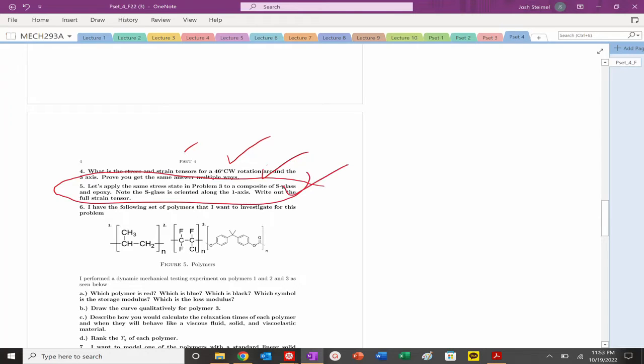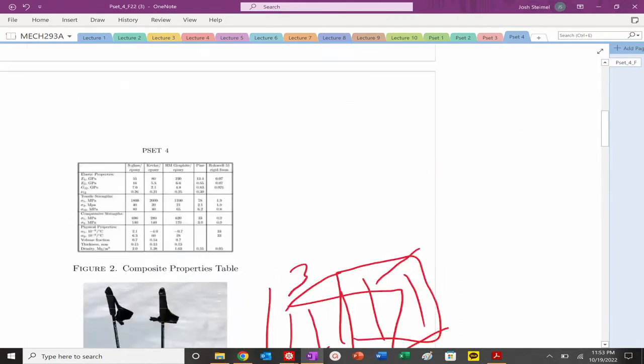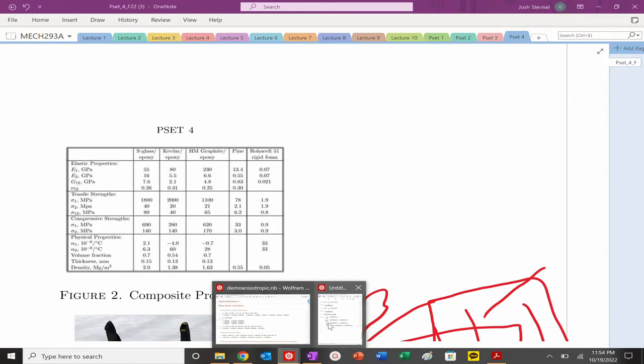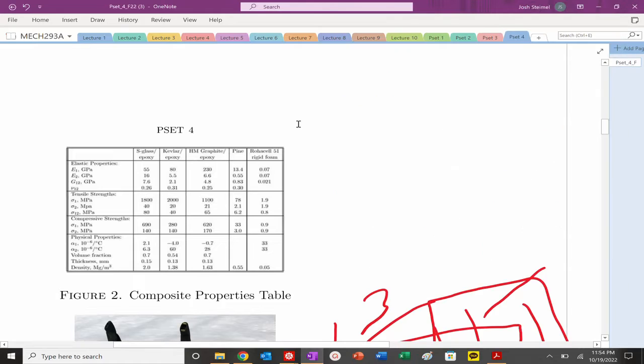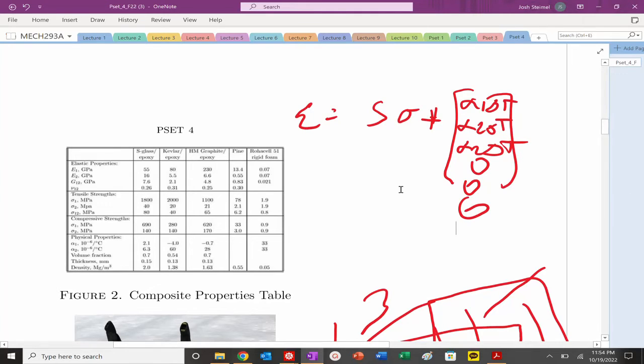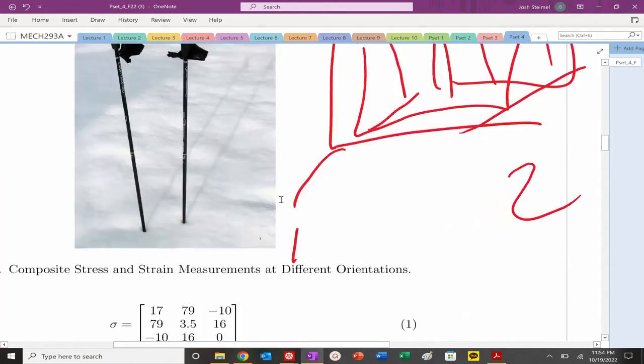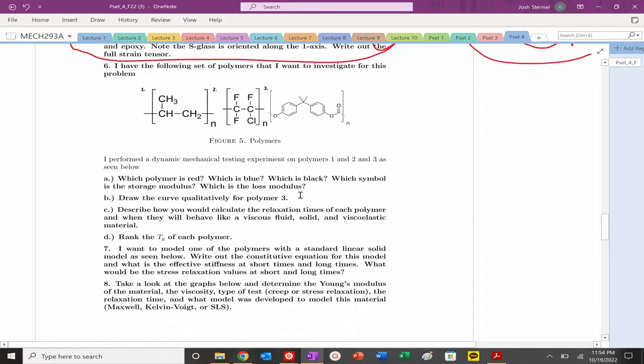For extra credit on thermal expansion: we would simply add a 1×6 vector of alpha_i · delta_T terms to our strain expression. So the strain vector would include alpha_1·delta_T, alpha_2·delta_T, alpha_3·delta_T, and so on. This may appear as a sub-problem on a take-home exam.